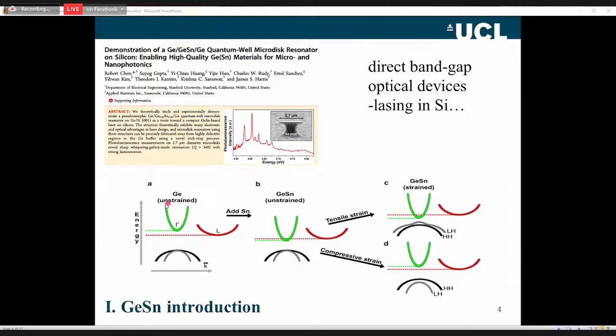If we look at the band structure of germanium, this is now in momentum space. The green is the conduction band at the gamma point, the so-called direct band gap. The black here is the valence band, so this is a hole band. And you can see here this red band, which is another part of the conduction band, is actually the lowest part of the structure. The lowest energy is in the L band. So this material is indirect. Germanium is indirect. It's not very good for optical devices.